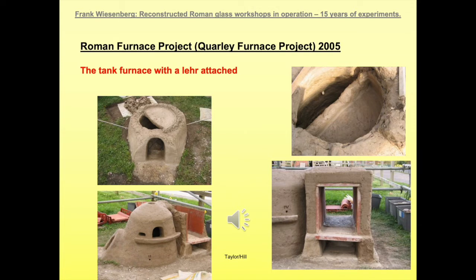The tank itself wasn't too successful since it developed a couple of cracks during the firing process. So the glass, which was inside this kind of tank, just found its way down into the fire pit. But nevertheless, this tank furnace had to be kept in operation at high temperatures just to power the annealing chamber and to anneal the vessels thoroughly.